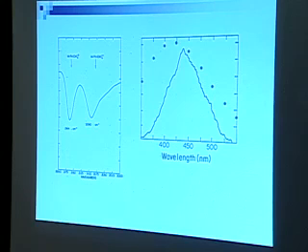You could also do fancier things like some spectral electrochemistry in the optical region in the cell. You can't do this experiment easily in the cell because it's IR, and the cell has water in it, and the two things don't get along. So we did an optical experiment where we looked at the diffuse reflectance spectrum of a sample of nickel ferricyanide, and this is a different spectrum between the ferri and the ferro, and you see this subtraction peak.